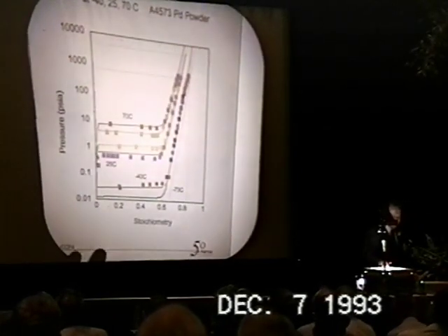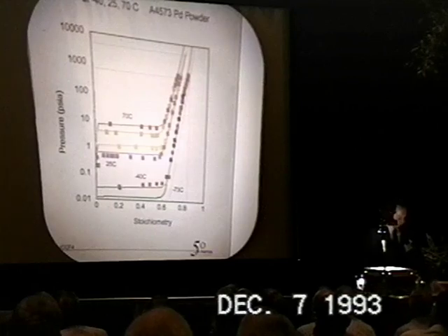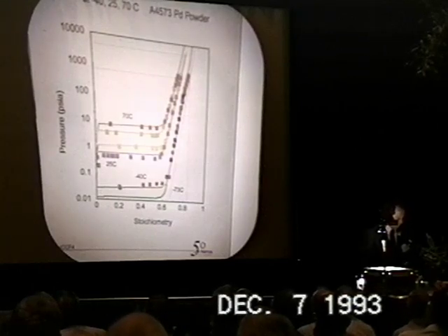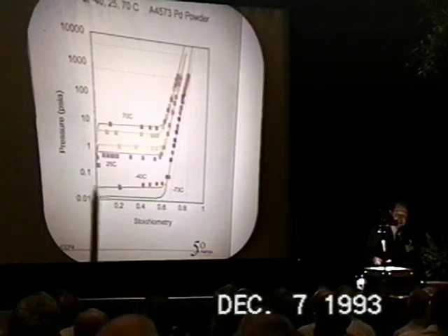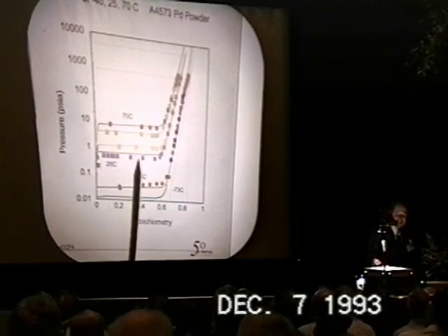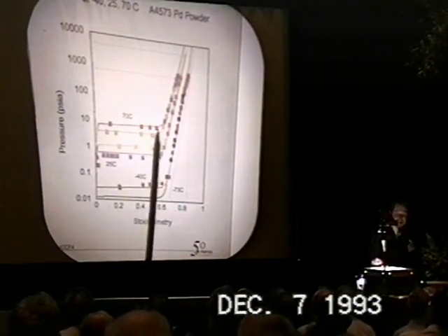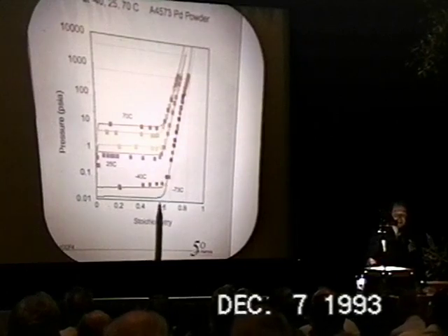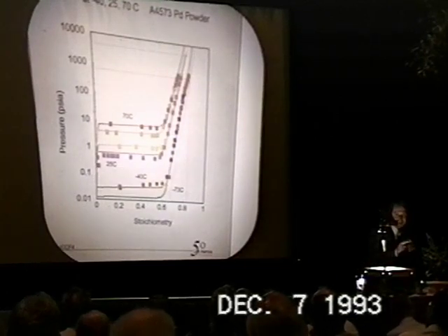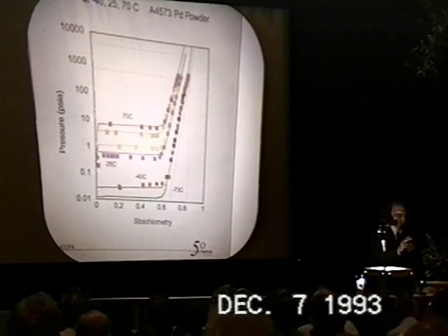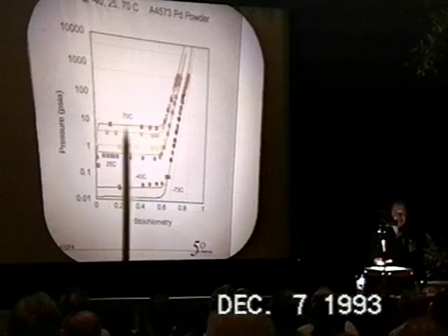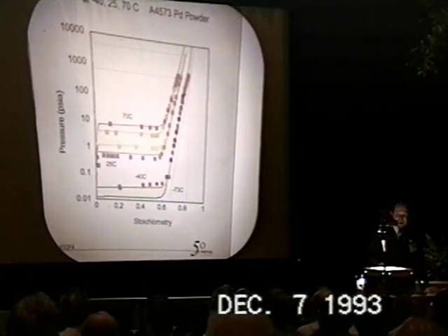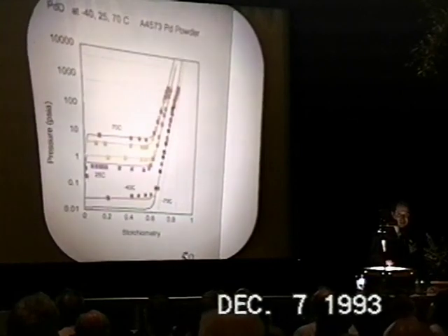Just a quick sketch of the region we're working in. We are working with palladium with deuterium gas overpressure, primarily room temperatures and pressures from 400 torr up to a couple hundred psi, so in stoichiometries from 0.6 up to about 0.72. The tritium measurements we do are of the overgas above the palladium, and at the end of the experiment, by heating the palladium up, we drive the residual gas out and also measure the tritium in that gas.